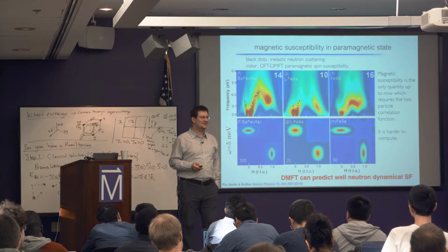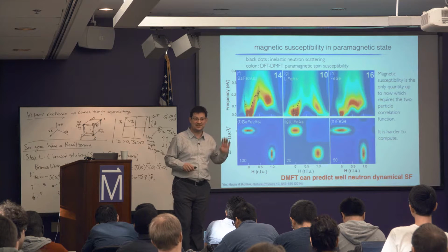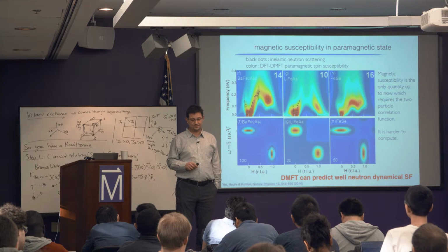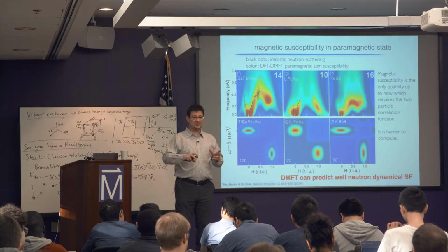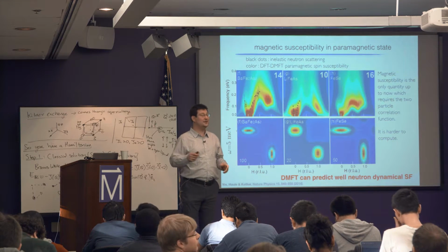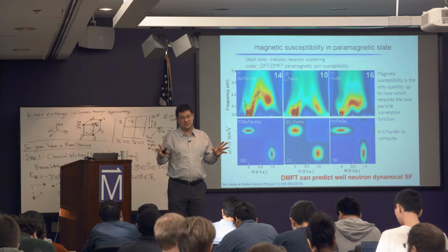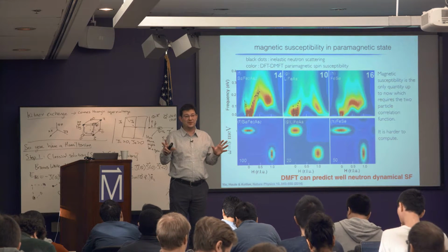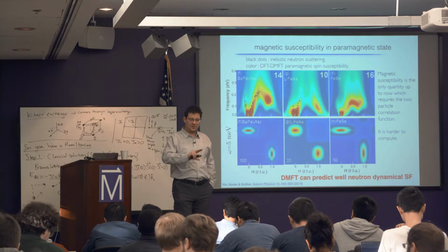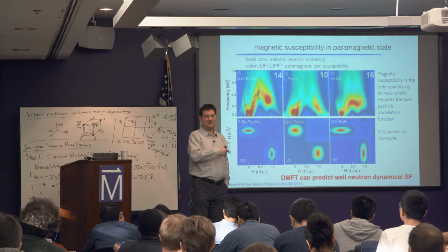Well, yes and no. I mean, the trick of the spin fluctuation theory, if you want to get decent spectra or similar spectra, you need to go into the ordered state. So you need to go into the mean field state. You have to tweak the amount of the long-range order, and then somehow you get some reasonable spectra. There were some papers where they produced reasonable spectra. Okay, but of course you have tuning parameters. Is it true that in those approaches, the origin of the incoherence is completely different? Completely different. Exactly. In the ordered state, these are interpreted as magnons, but here they are paramagnons.